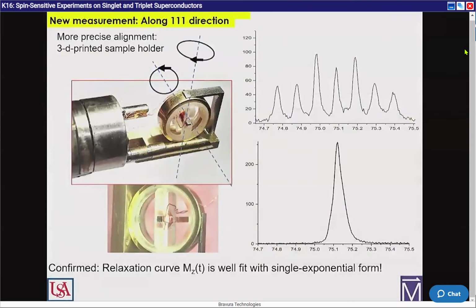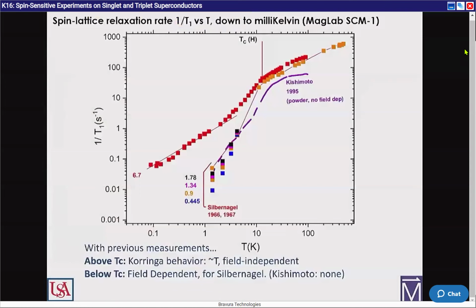Yay. Okay. So what did we get when we measure down to 100 millikelvin, thanks to the facility at SCM1 in MagLab? Here's our first set of data in red, and we have also included two other previous studies that have done something like this up to just above 1 Kelvin. For Silbernagel, we're in agreement that above TC you have your Korringa behavior and field independent.